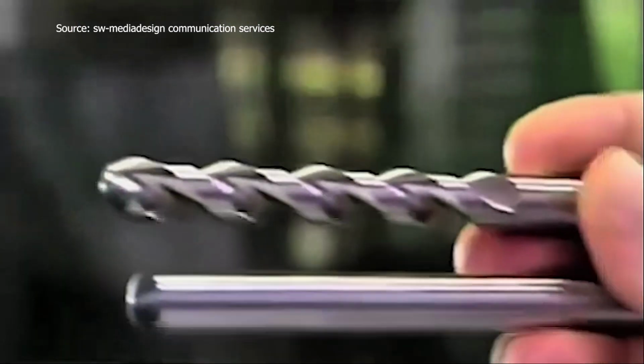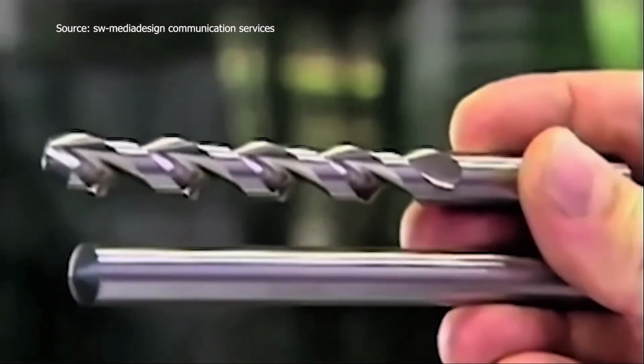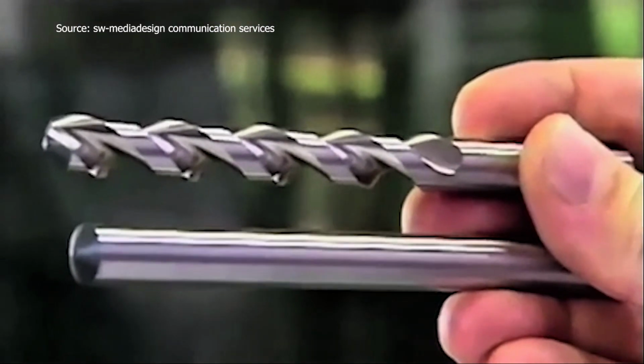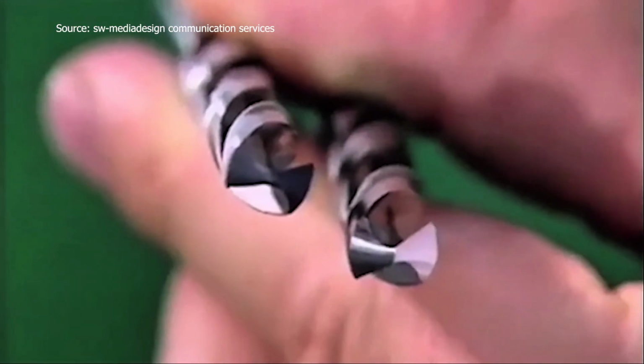Some drills receive a black oxide surface through steam treatment. This involves exposing the drills to superheated steam in a tempering furnace for about an hour, enhancing wear resistance and corrosion protection. High-performance variants are coated with hard layers such as titanium nitride, TiN, titanium aluminum nitride, TiAlN, or titanium carbon nitride, TiCN.